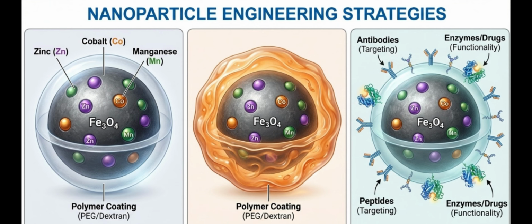Additionally, biological behavior and treatment efficacy are significantly influenced by surface chemistry. Coatings like PEG, dextran, or chitosan increase colloidal stability, decrease immune recognition, and prolong circulation duration, because bare iron oxide nanoparticles have a tendency to agglomerate or oxidize in physiological fluids. More sophisticated shells can provide multimodal functionality. Gold shells allow nanoparticles to function as dual-mode agents for both magnetic and photothermal therapy, while silica coatings allow chemical modification for drug loading. Therefore, simultaneous hyperthermia and NIR light heating are made possible by gold-coated MNPs, boosting temperature rise at lower field strengths.